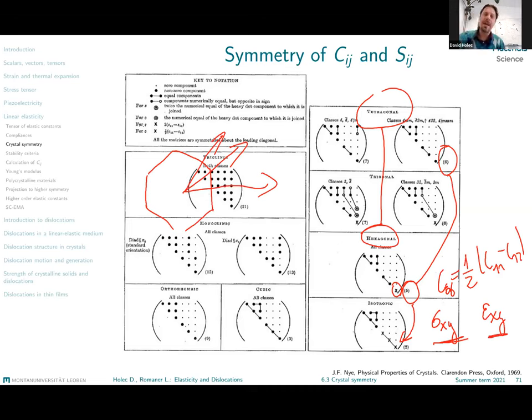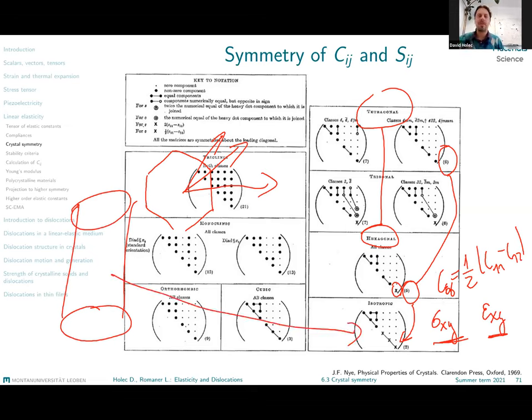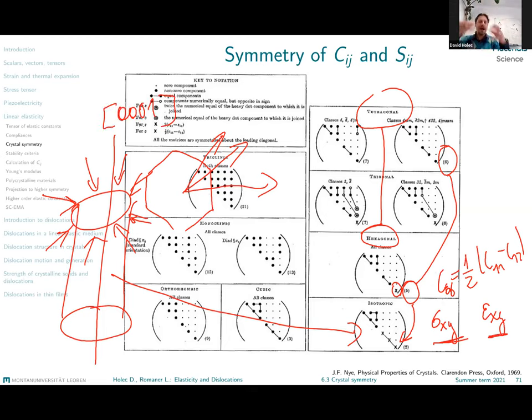In other words, if you make a cylinder out of elastically isotropic material, of course, then the deformation in all of those directions is going to need the same force in all of those directions. What we are saying now is that if we do the same thing for a hexagonal system, where this is the 0001 axis, the hexagonal axis, and out of this hexagonal system, for example titanium, we carve out a cylinder, this cylinder will exhibit isotropic elastic response in the directions perpendicular to this cylindrical axis. Quite a cool feature, isn't it?